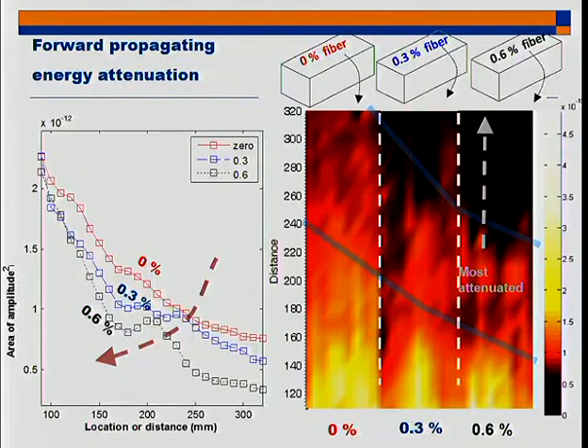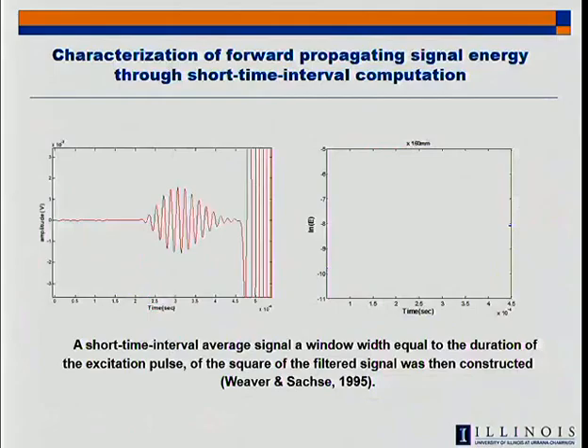So what we found is that we can use the forward propagating velocity and forward propagating attenuation, and if we're very careful, we can find some information and use it to distinguish cracking. But it maybe is not as sensitive as we would like. And so we've come up with a different approach, which I won't talk about in so much detail because we're still developing. It's a new area of research for us. But I will talk more about these forward propagating waves.